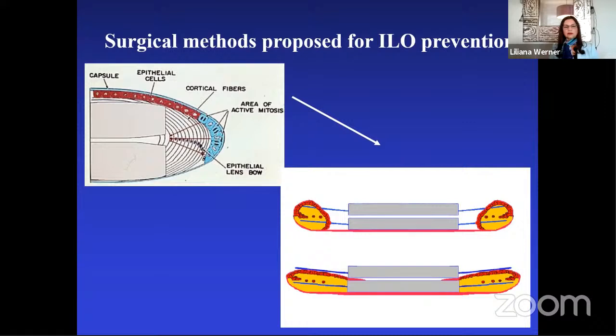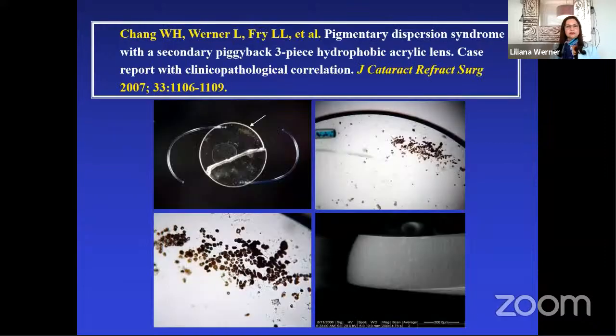To avoid this problem, besides avoiding the use of 2 hydrophobic acrylic lenses inside of the bag, you can perform a capsulorhexis with a diameter that's larger than the diameter of the lens optic, or implant one lens in the bag and one in the sulcus. When fixating a piggyback IOL in the ciliary sulcus, we cannot forget that if the lens has optic edges that are square and irregular, the lens can cause pigmentary dispersion in this location.